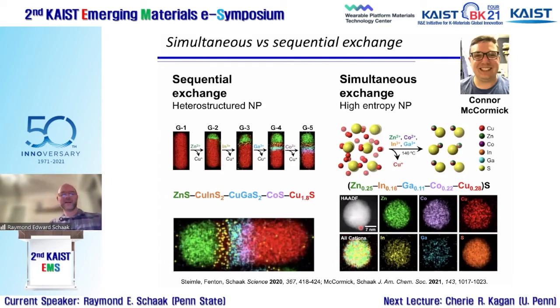And just as the final thing to show where even more excitement can come from, the exact same reaction that formed this fifth generation nanoparticle, where we started with a nanorod of copper sulfide, installed a zinc sulfide tip, then copper indium sulfide, copper gallium sulfide, cobalt sulfide. The same reaction carried out sequentially with sequential injections.